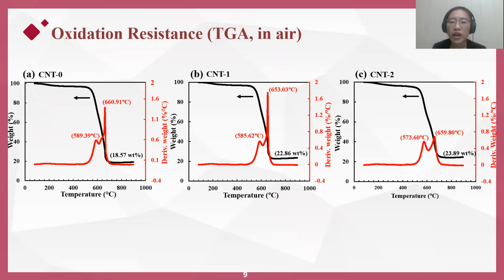With an even higher water concentration in the CNT2 group, the second derivative weight peak occurred with similarly lower intensities, which may suggest a transition to a more homogeneous distribution of CNT sizes and wall counts. We have also noticed a surprisingly increasing trend of the catalyst residue from 18% all the way to 24%. To better understand this trend for the CNT0 and CNT2 groups, we took out samples during the TGA at 600, 700, and 800, and we examined the samples using SEM and EDS.